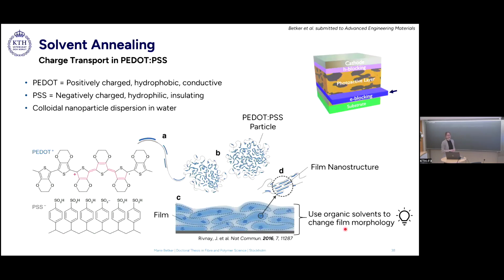So I already mentioned PEDOT-PSS before. It's a conductive polymer blend. So this means we have PEDOT. This is the conductive polymer, but it's also hydrophobic. And then we have the PSS. It's insulating, non-conductive, but it's actually hydrophilic. And so what happens when you mix them together, they form nanoparticles, where the conductive PEDOT part is in the middle, and the insulating PSS is around it as a shell, but makes it water soluble, so we can actually use it in solvent-based techniques like spray coating.